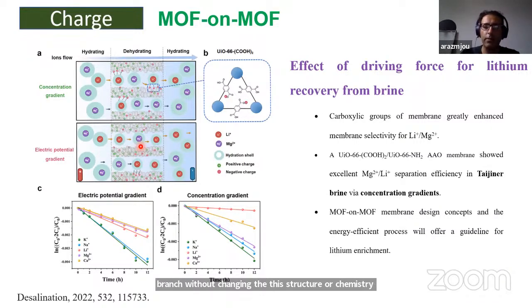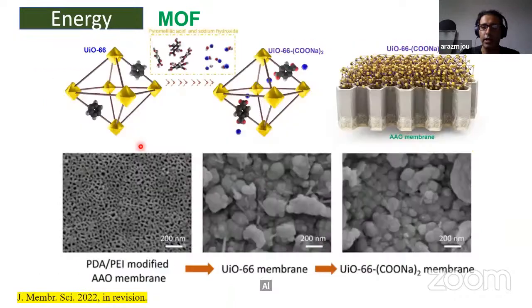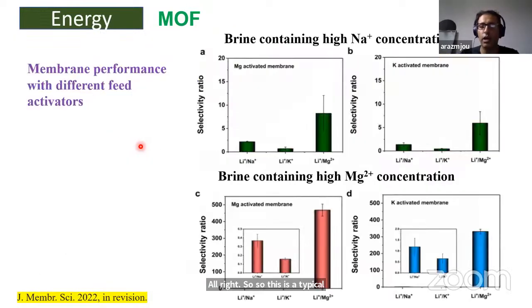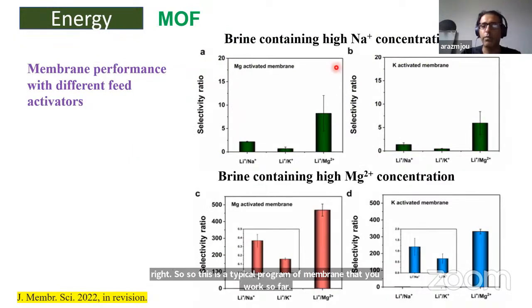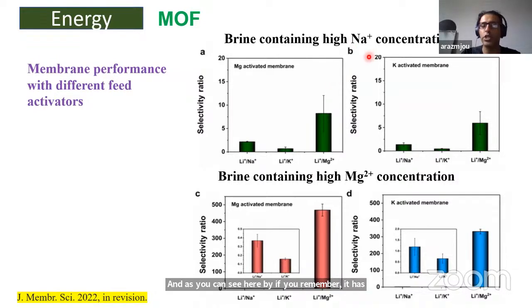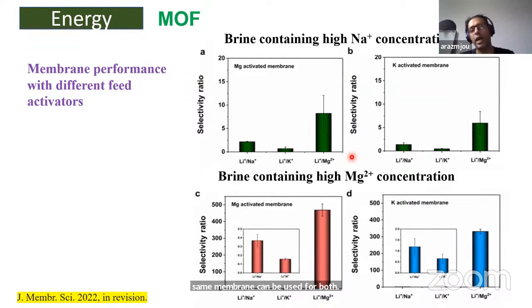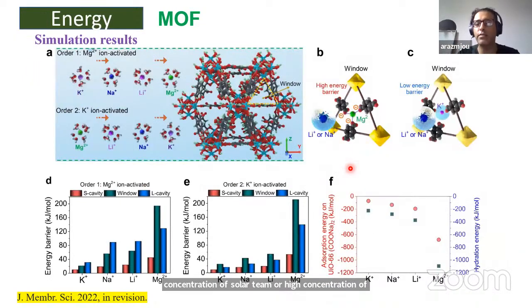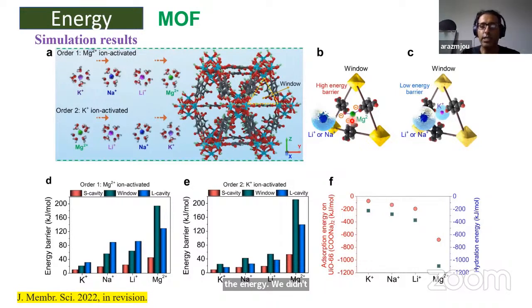All right, so this is a typical programmable membrane that we have worked on so far. As you can see here, the same membrane can be used for both high concentration of sodium or high concentration of magnesium, and that provides the flexibility to use a specific membrane for a wide range of brines. The concept comes down to the fact that we can implant or alter the energy barriers within the nanostructure of the membrane by conditioning it with a specific cation. In this case, for example, we conditioned the membrane with potassium, and here with magnesium.